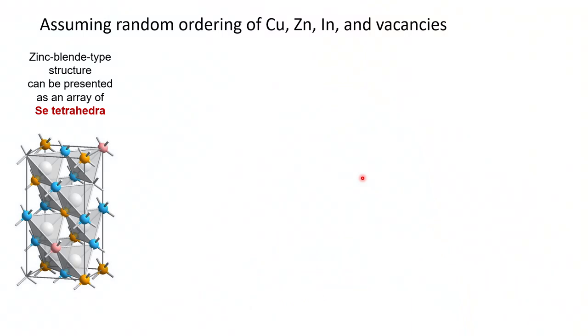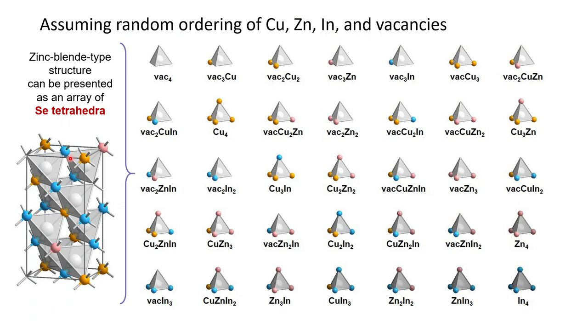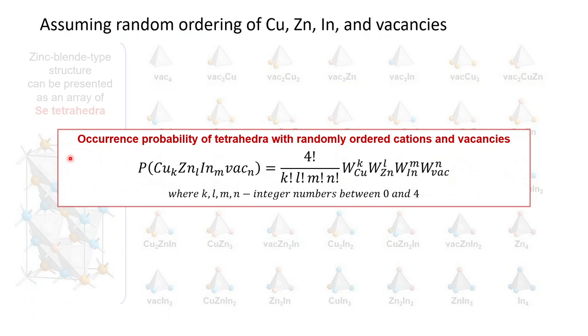But our goal was not to find another one, it was to explain why these peaks are happening and generally what is going on. So the first step was, let's assume that we have a random ordering for the cationic sublattice, for the copper, zinc, indium, and vacancies. So as you know from the previous slide, the zinc blende type structure can be presented as the array of selenium tetrahedra, and there are 35 theoretically possible tetrahedra around this selenium. This seems fairly complex, but it's actually quite simple, because what we can learn from the combinatorics is that we can calculate the occurrence probability of each of these tetrahedra, and what is simple is that the percentage of the tetrahedra would be directly proportional to the mass fraction of the components that are there, plus a small combinatorial factor.